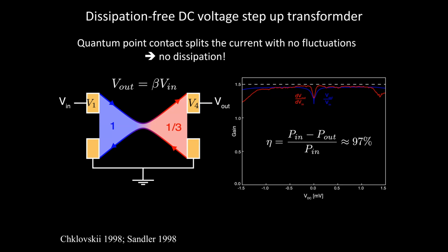So you can ask, for this voltage transformer, how close is it to this dissipationless limit? You can measure, for example, the power efficiency. How often is this process happening rather than some other process? And it turns out to be very close to perfect. So you get something like 97% efficiency and a gain of 1.47 rather than 1.5, because essentially every time you try to inject an electron, it splits into two positively charged e/3 quasiparticles and one negatively charged e/3 quasiparticle. It just works very well. In fact, the only reason that it doesn't work perfectly is that this is, strictly speaking, not a stable fixed point of the RG. And so, at very low energies, the junction wants to separate itself.